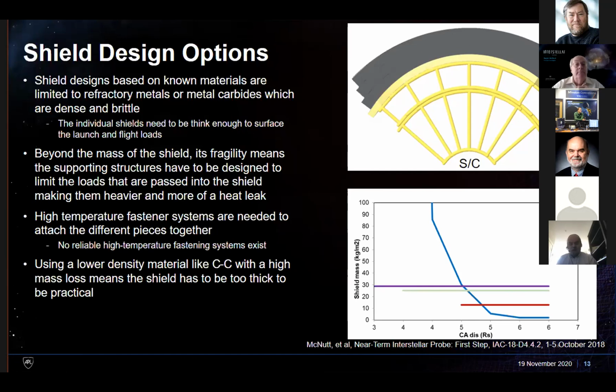It's kind of the thing they're doing on NGST, where you have layers of material, and there's heat coming in the front end, and some of that heat is drifting out through the sides, and that allows the temperature to be dropped. The more layers you have, the more the temperature drops, and eventually you get to the point where you can drop the temperature down to a 2,000-ish range, where you can start using a regular shield. Use that regular shield to drop the temperature down to 600 degrees, where you can use that titanium, which drops it down to the spacecraft, which is again running kind of at room temperature.